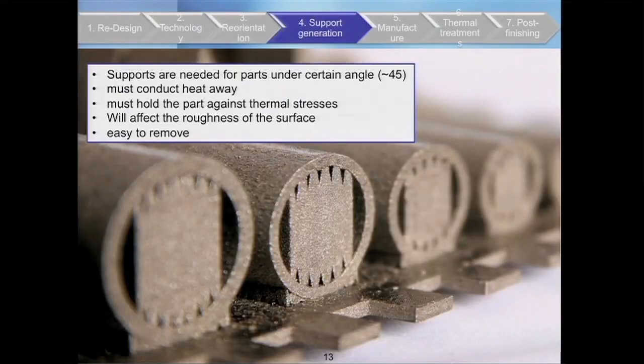Supports. Supports are what you can see there, and they have two functions. First function is to really support the structure that you are building, and the second one is to evacuate the heat from the part that you are building towards the building plate. It's not the same, the supports that you need for electron beam melting, that normally you need less supports because in the preheating step you are already pre-sintering powder, so your powder bed is acting like a self-supporting bed, and that is not the case in the SLM. But anyway, you need the supports to evacuate the heat.